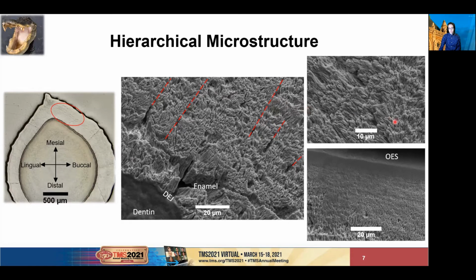The top right micrograph showcases the divergence within a column. The crystals are fanning out from the center axis of the column. Progressing through the enamel thickness, the hydroxyapatite crystals become increasingly aligned, making it more difficult to distinguish individual columns. The final SEM image on this slide shows a fairly sharp gradient near the outer enamel surface. Nanocrystal size and porosity decrease, enabling higher and higher packing density.